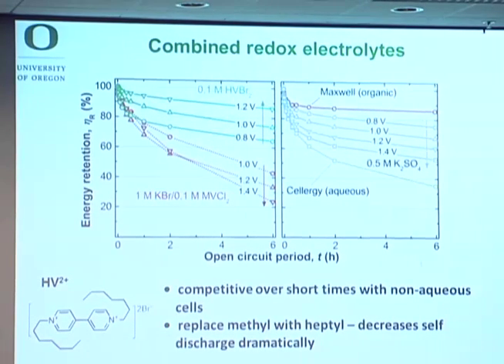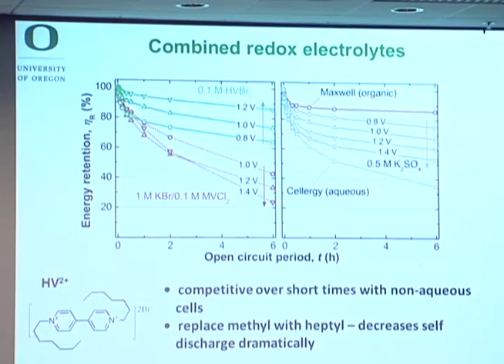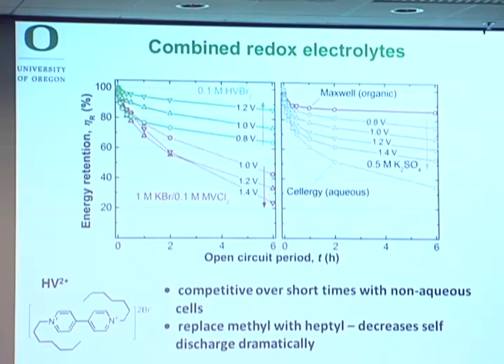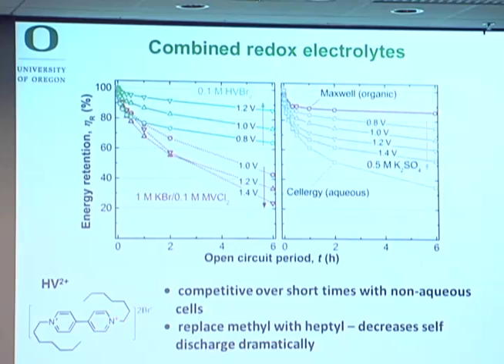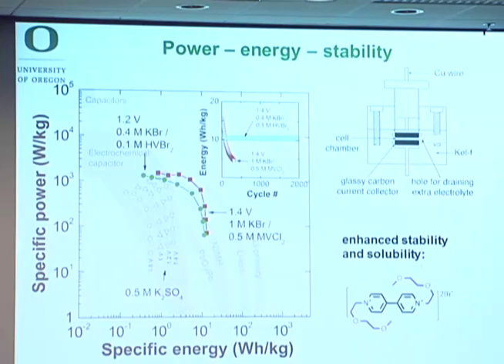But what's interesting is if you replace the methyl-viologen with heptyl-viologen, this was known from the electrochromic literature to have better cyclability. It also has lower solubility, so once you make the singly reduced species, it's going to absorb probably more strongly on the activated carbon. Now, the self-discharge rate is actually very slow. The problem with this is, of course, its concentration isn't that high.